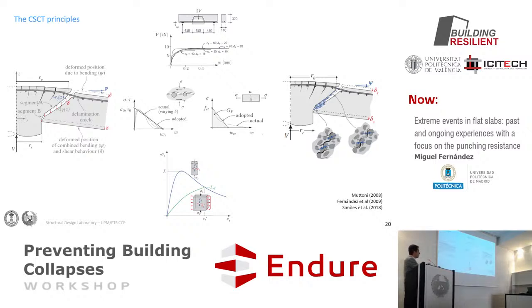So from top to bottom, you can say, okay, here in the delamination, as you know from the Baumann-Rusch test, you can calculate that delamination is rather plastic, because once you start delaminating, it delaminates at a further distance. So you can calculate the contribution of dowel action. You can calculate within this crack, which is the largest part, the aggregate interlock. So opening and shearing, as you see, you can transfer perpendicular and tangential stresses or residual stresses. And also in the bottom part, which is very active, you get the compression, the response of concrete in compression. This response depends on the state of lateral stress that we are having.